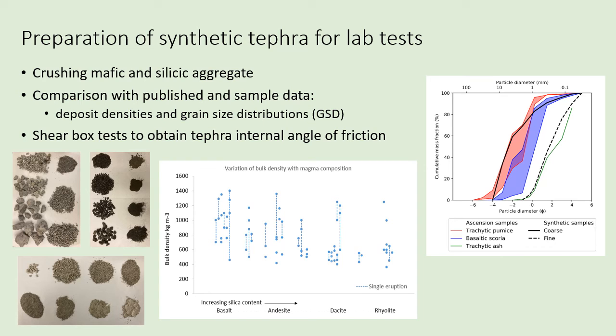I have also investigated the grain size distributions. I have some Ascension samples collected by Rich Brown from Durham University. The pictures on the left show these sieved samples, and the plot on the right shows the grain size distributions for the samples of pumice in pink, scoria in blue, and ash in green. This plot has grain size on the x-axis, with finer distributions plotting to the right. The black lines show the grain size distributions of my synthetic samples, and as you can see, these are very similar to the natural samples. These are the distributions that I'll be using for the sliding tests.